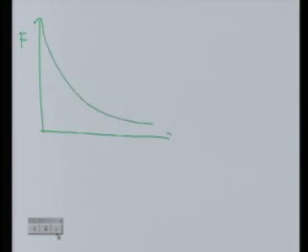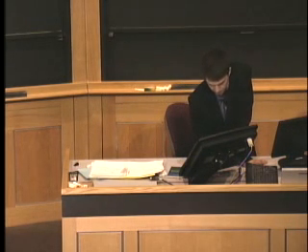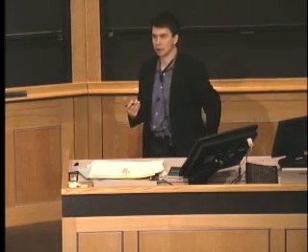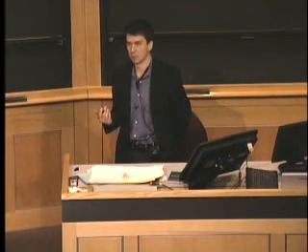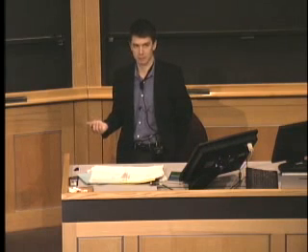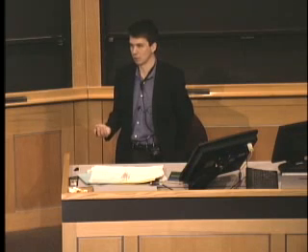You know, if you have an embedding function as a function of rho, if you're working, say, at this density, let's say the density of the bulk, and you're studying bulk problems, you could take the slope of this, take the linear term, make a linear approximation to that, and add that to the pair potential, and now you wouldn't have to worry about the embedding function. So at constant density, pair potentials are actually pretty good.